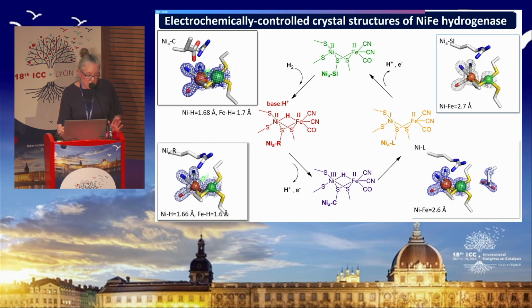Of course, X-ray diffraction is not the best way to be looking for protons in structures, and we're never going to see that. And so the other thing we've been doing at the other end of the crystal size dimension is growing very large crystals that we can use for neutron diffraction. And we've been able to collect at the nickel C redox state the first diffraction data on these large crystals at the neutron source at ANSTO in Australia, and we have further beam time coming up at Oak Ridge later this year. So we're hopeful of being able to begin a series of neutron structures.